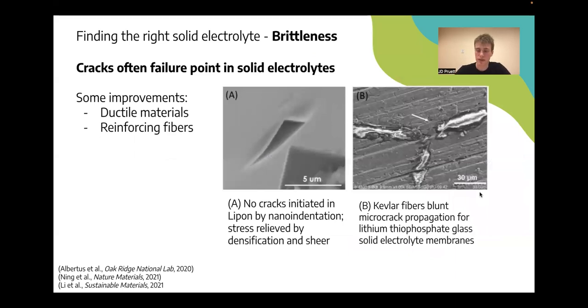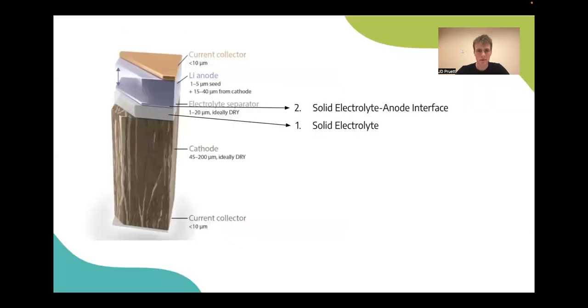There have been some improvements on this front in basically two ways. The first is by using ductile materials. So LiPON, lithium phosphorus oxynitride, is a commonly researched electrolyte. And as you can see, what happens is when you try and crack it, it acts ductile. It actually just gets more dense in some places than others and relieves that stress by shearing. Similarly, other researchers have experimented with putting Kevlar into these solid electrolytes, and these Kevlar bits prevent the propagation of cracks through the electrolyte. Now I'm going to move on to the electrolyte anode interface.